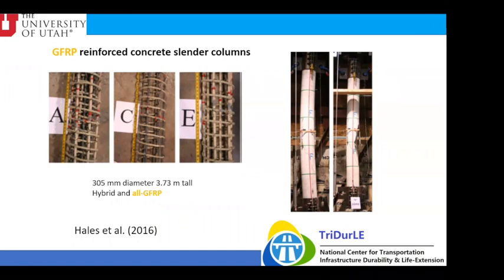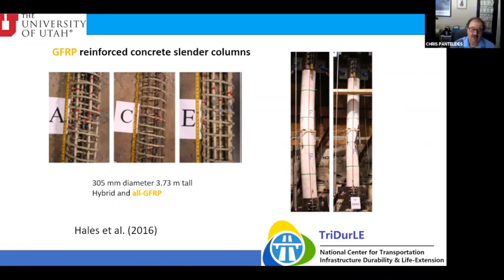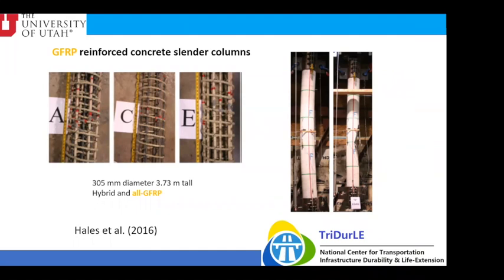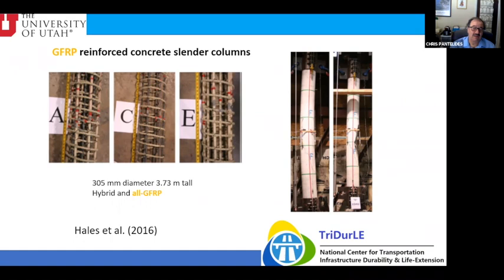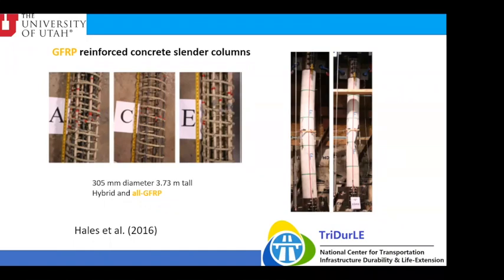Yeah, I understand. And my point was actually glass might be better than carbon in this scenario in terms of reducing the ingress, because if your interface has no ITZ, or interfacial transition zone, or a weakness, yes, a pathway for moisture and chloride to go through. Right. And another thing about carbon touching steel, I think it may actually, what you mentioned earlier, accelerate the corrosion. That's a debatable one because I've seen different publications. Some say the fiber is actually beneficial. Some say it's detrimental. So, yeah.